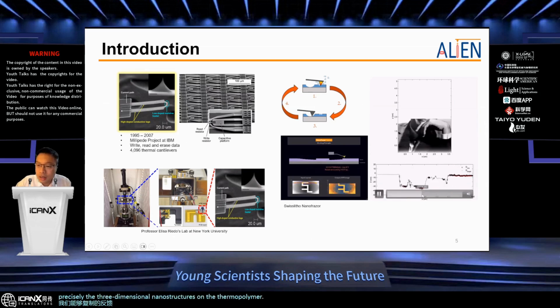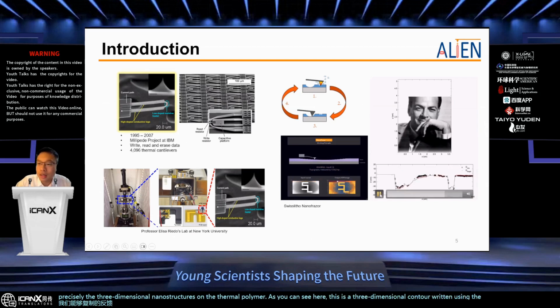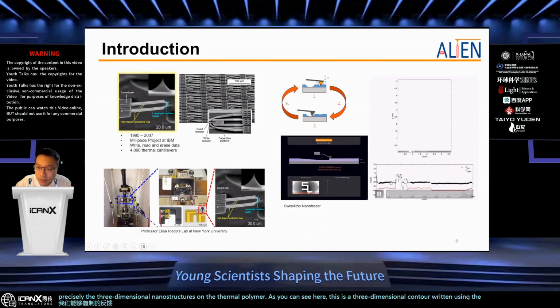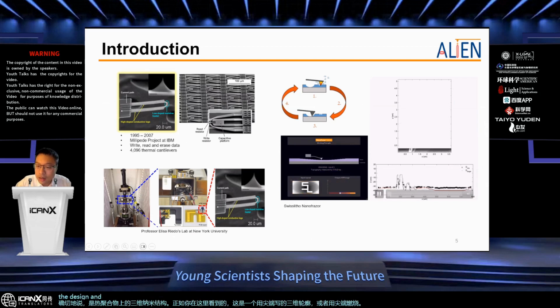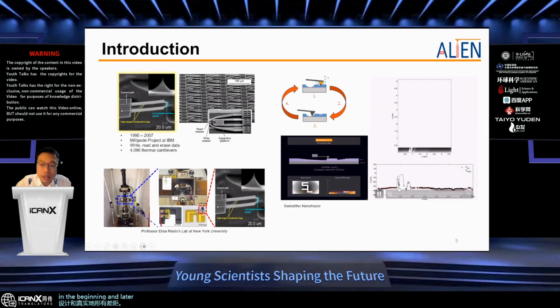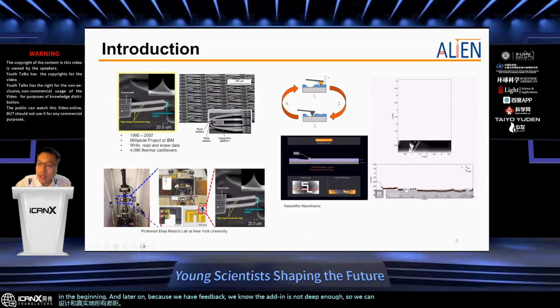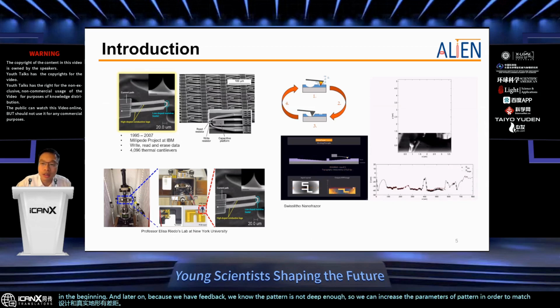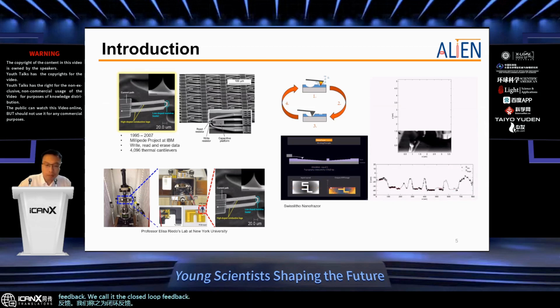As you can see here, this is a three-dimensional contour written using a tip, or burning using a tip, on the polymer. At the very beginning, the design and the real topography have a gap. And later on, because we have feedback, we know the pattern is not deep enough. So we can increase the parameters of patterning in order to match this topography and the design. So this is the power of feedback. We call it closed loop feedback.